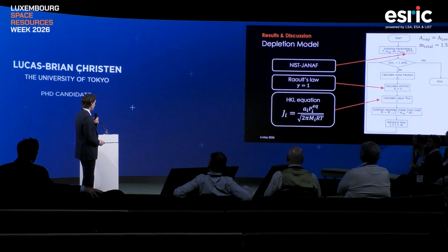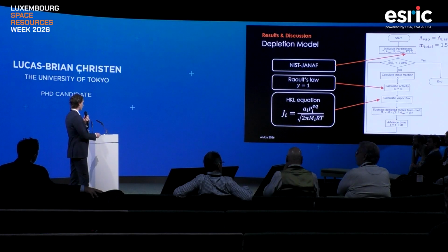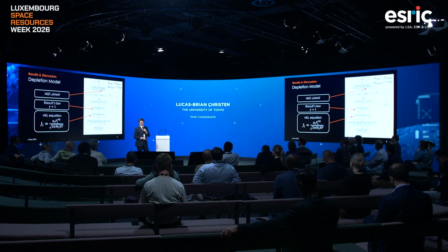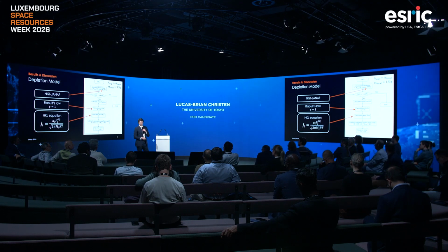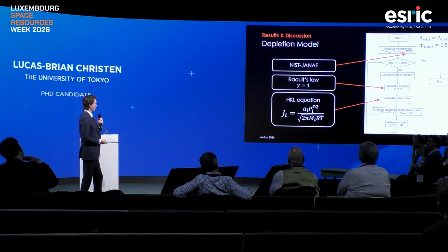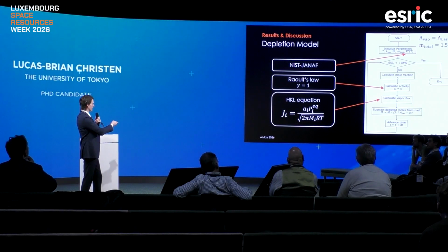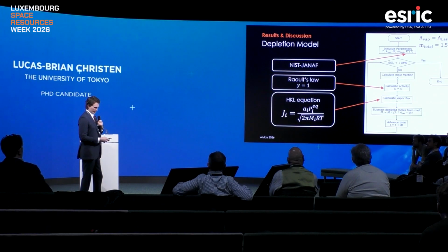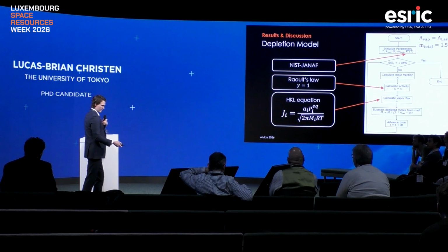Then we can go ahead and calculate the vapor flux of each species and sum that up using the Hertz-Knudsen-Langmuir equation with this ideal solution. That iterates through time steps until we reach a silicon dioxide content of 1 weight percent or less. And then we go ahead and end that iteration. That gives us the oxide species flux over time, and we can plot that.